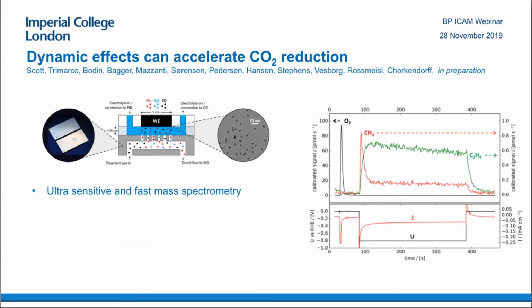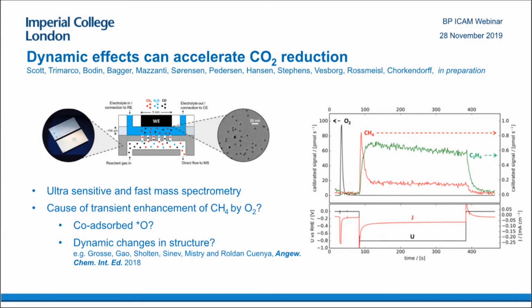What we found was that when we put in oxygen, which we did by mistake initially, before we carried out the reaction, we could selectively favor methane production just for a few seconds over ethylene production. By changing the potential at which we adsorbed oxygen, we could change the amount of this methane you see at the beginning of the transient. If we didn't add oxygen at the beginning of the transient, this curve was completely flat. The steady state activity is the same as the initial activity. So this is a very interesting phenomenon.